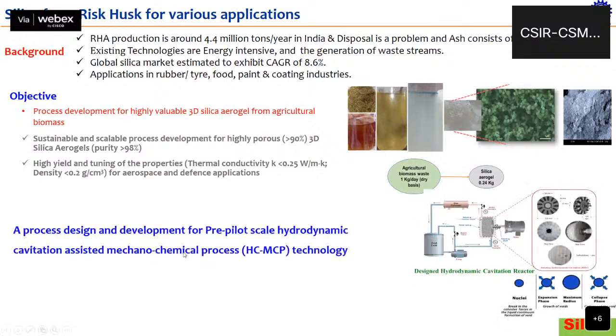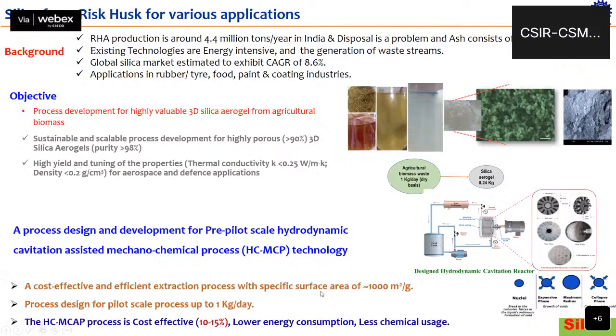Another proposal we received is to make silica directly from rice husk. In this case, they are working on converting the rice husk to silica using a cavitation process, that is, mechanochemical hydrodynamic cavitation assisted process. The beauty of this proposal is that we can generate silica with particular shapes and sizes, continuously, and it can be piloted up to 1 kg level. This silica can be used directly without all the energy intensive processes, so we propose it can be used in different applications.